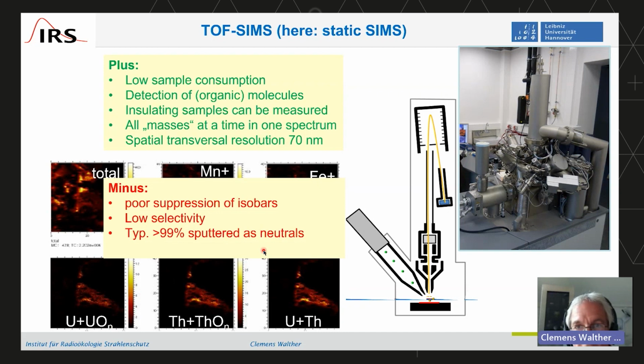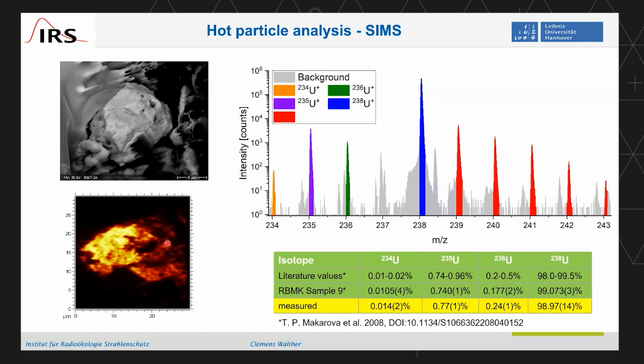Also with secondary ion mass spectrometry, you have some downsides, and the downside here is the poor suppression of isobars. You have a low selectivity, and when I imagine the sputter process, 99% of what you sputter off is neutral atoms, and the neutral atoms cannot be extracted into the mass spectrometer, only the ions can, so you throw away 99% of what you produced and detect only 1%. Still, you can get nice information here.